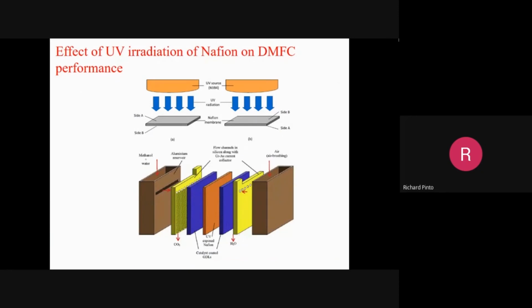Okay, this is another important piece of work which we did: reduction in internal resistance of the Nafion. That is the key, right? You have to reduce the internal resistance of the Nafion by whichever way you want. One of them is to expose it to UV rays. People have done a lot of work exposing it to gamma rays, electron beam radiation, and so on. We did some work by exposing it to UV radiation, and we just used the UV rays from the mask aligner, MJB4.